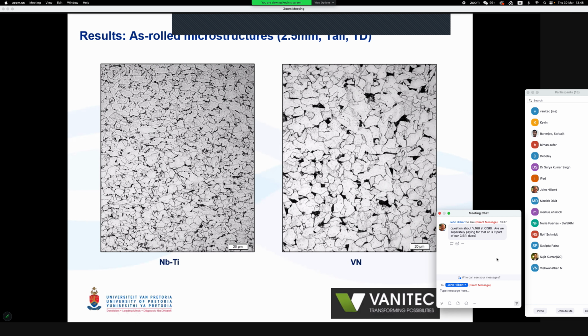Just looking at some microstructures, this was a 2.5 millimeter, comparing the niobium titanium grade against the vanadium nitrogen grade. As we know, there's more grain refinement that occurs during the thermomechanical rolling of vanadium steel, hence the finer grain. We all know that. But most of the strength comes from the precipitation strengthening after rolling.